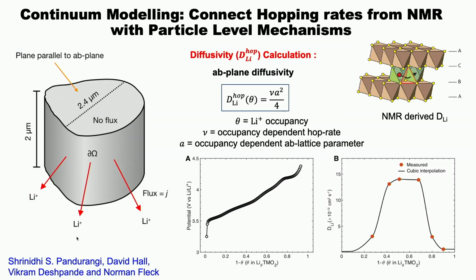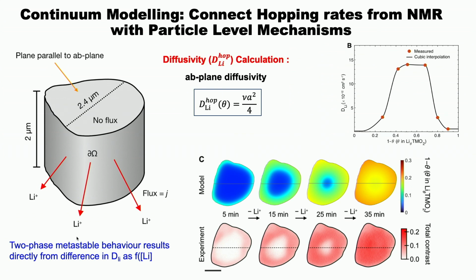And what's nice is, because now we have the lithium diffusivity from the NMR, that's why I went through the exercise and showed you the NMR. We had the hopping frequency, we know the distance over which a hop occurs, so we can then use that to calculate the diffusivity from the NMR. We know the voltage curve tells us the energy, the delta G, associated with pulling the lithium out of the structure. And so we can put that into a nice continuum model. We're now collaborating with Norman Fleck and Vikram Deshpande, and Shri was the postdoc on the project, who built a much better continuum model with a particle that looked like our particle, and he was nicely able to replicate the shrinking core model of the system. So that was the NMC.